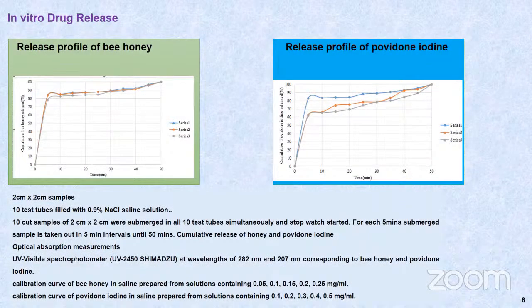In vitro drug release profiles of bee honey and povidone were analyzed through UV spectroscopy separately for the three samples that we prepared, and the results showed that there is not much burst release, while the release profiles of bee honey in the three samples were similar. In the povidone release profile, while increasing weight percentages, the drug release rate decreased. The third sample, having the best beaded nanofibers, had the slowest drug release, further backing the incorporated nature of povidone.